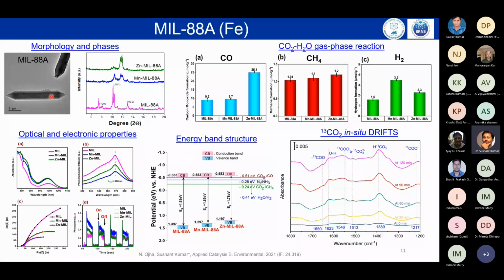In this structure, it is more of an organic-inorganic mix, where the inorganic part is FeO clusters and the organic part is a hydrocarbon framework. And in this, we have doped manganese and zinc. You can see that there has been a distortion of the XRD peaks, and the reason we don't know, but what we have seen is that zinc and manganese both were present. This has been synthesized using the hydrothermal reactor, and there could be a more complex mechanism which could happen here, but that was not part of our interest as of now.